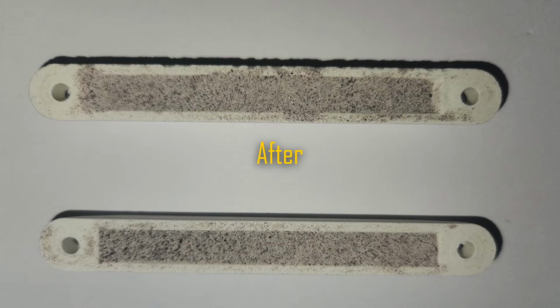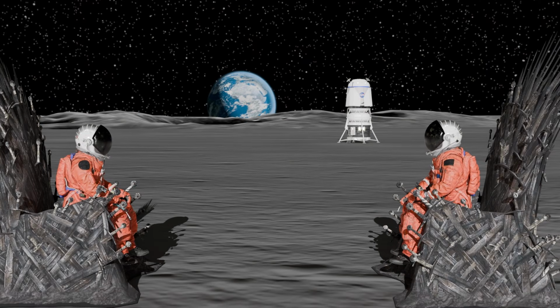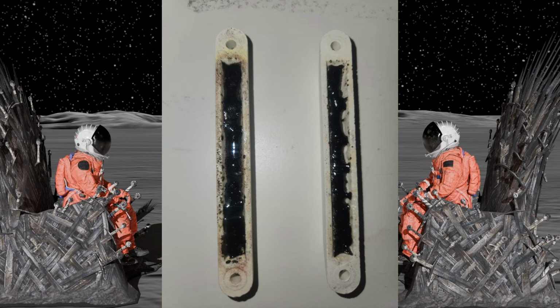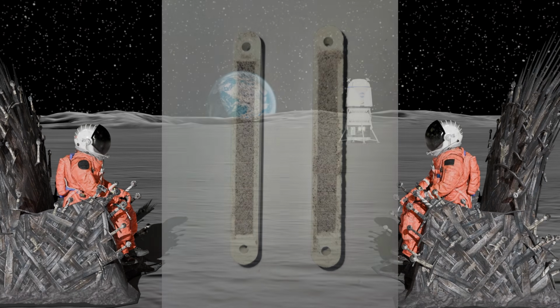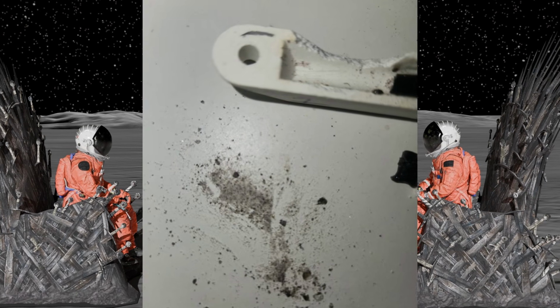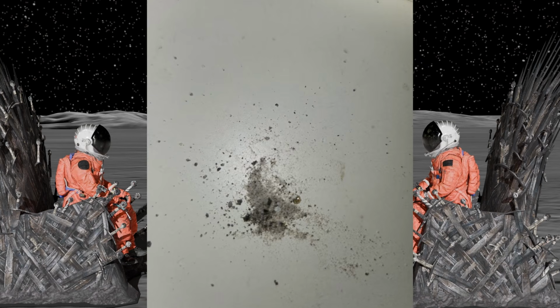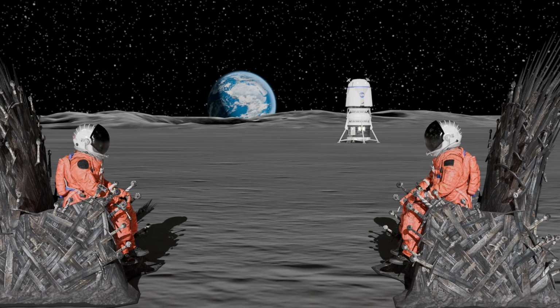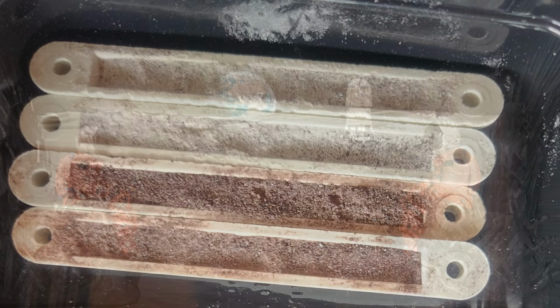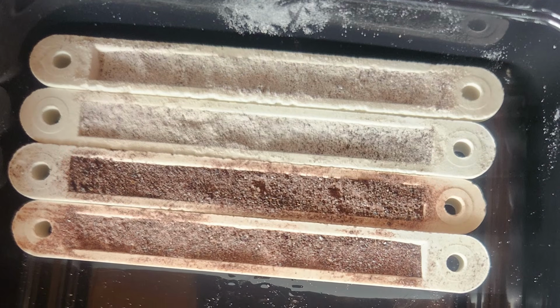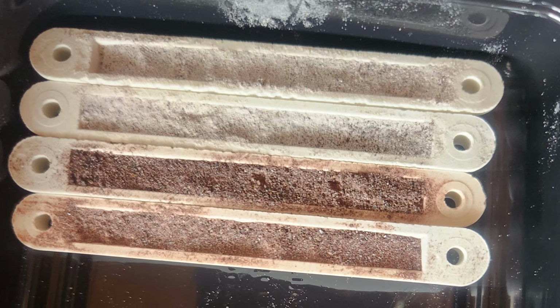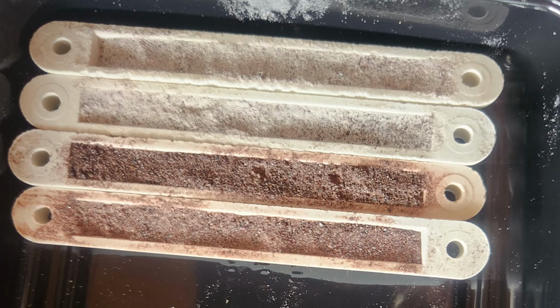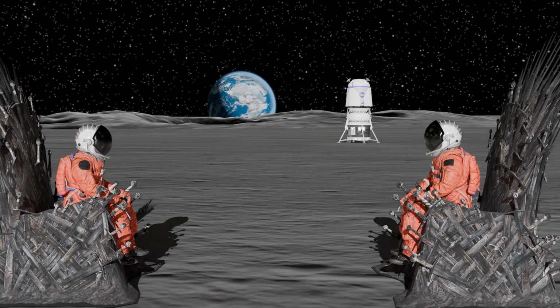And yes, we tried obviously different temperatures. I have temperatures here. We tried everything from 1550 degrees Celsius, which did create a glassified regolith, and at temperatures that were much lower. And we tried at 750 Celsius. It was pretty much like sand. It was free flowing. The particles were not stuck together. We did attempt sintering lunar regolith to see what temperatures it would actually fuse at. And we did find that around 1042 Celsius is when an optical change occurred on one of the samples, and then pretty much no optical change on some of the other samples as far as glassification until over 1150 degrees Celsius. So there's optimal ranges to produce the pure iron without melting it, which is extremely useful.